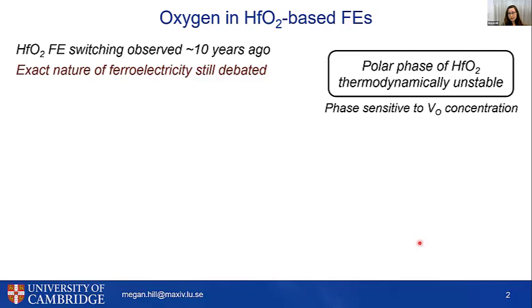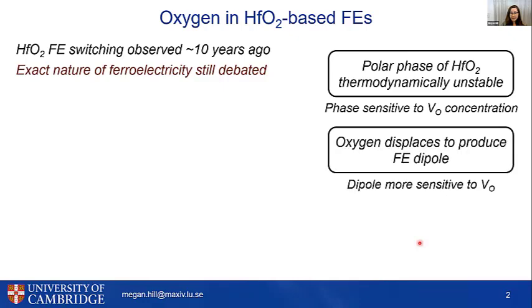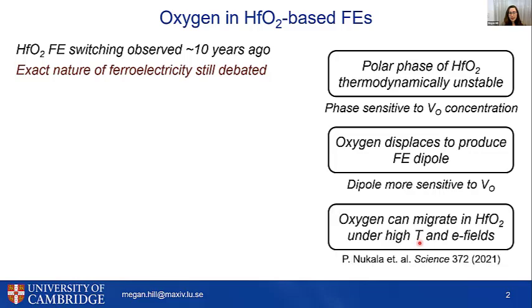So this is quite a complex material because the polar phase of hafnia is thermodynamically unstable. So it's sensitive to oxygen vacancy concentrations. And the oxygen itself is actually the dipole, the atom that displaces to produce the dipole of ferroelectric hafnia. So then obviously it could be sensitive to oxygen vacancies. And finally, it's been observed that oxygen can actually migrate in hafnia at high temperature, but also at electric fields that are similar to those needed to polarize the material.